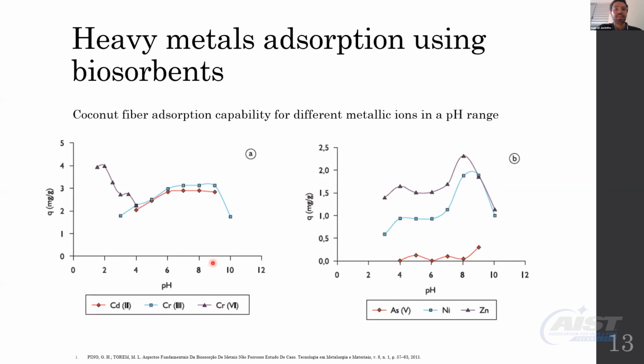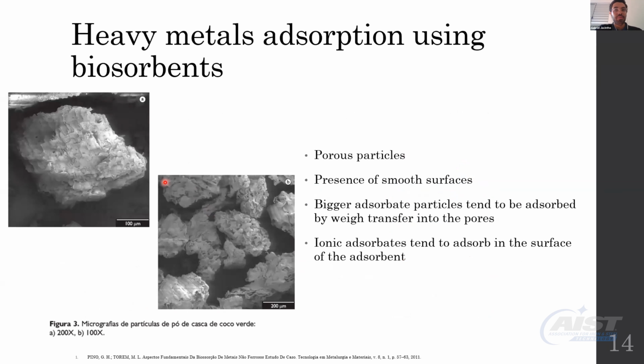Furthermore, metallic ions tend to form complex ions in some pH ranges when you increase the pH. Here are two images taken using a scanning electron microscope. It's possible to see that the adsorbent particles are porous, but there are smooth surfaces too. This is important because bigger adsorbate particles tend to adsorb by mass transfer or physisorption, accumulating in the pores, and smaller ionic adsorbates tend to chemically interact with the adsorbent surface, having chemisorption. The presence of both types of surface in the adsorbent increases its capability to adsorb different types of ions present in the wastewater.